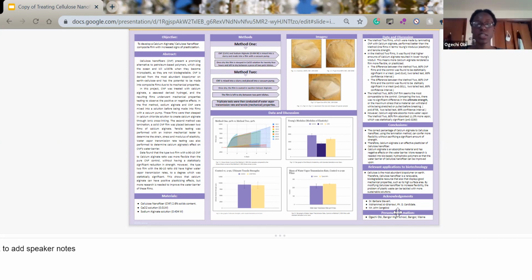I think that cellulose nanofiber films, because they are abundant in nature, would be more easily degradable, because if you just go into a forest, you see that trees biodegrade. There are also a number of mushrooms and bacteria that will biodegrade cellulose, as opposed to these corn-based polymers, which have perhaps had more manipulation from their plant process to their plastic process. Cellulose nanofiber is simply regular cellulose from the tree, just made into smaller fibers. So there hasn't been a lot of manipulation to the structure that would make it impossible for a mushroom or bacteria to break down the fibers.